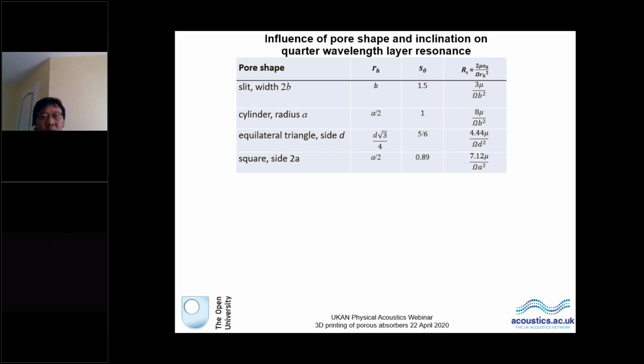And since that time, people have worked out lots of things for lots of different pore shapes, or at least 4 shown here. But other people, I think there's been work on hexagonal ones and annular ones. And anyway, the important thing is here that if you take a certain dimension value of B or A or D, then the shape that's always going to give you the highest flow resistivity for that given dimension is going to be the cylindrical. Actually, I won't talk very much about cylindrical ones. I'll talk mainly about slit ones, which in principle are the least advantageous from the flow resistivity point of view, but they're also relatively simple to model, and my computer doesn't like doing complex special functions.